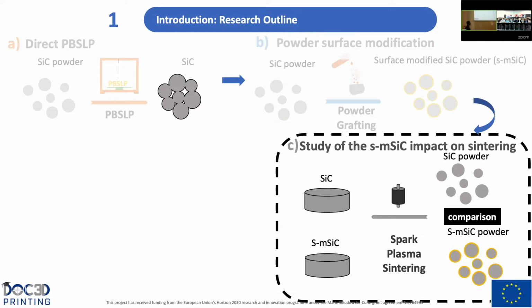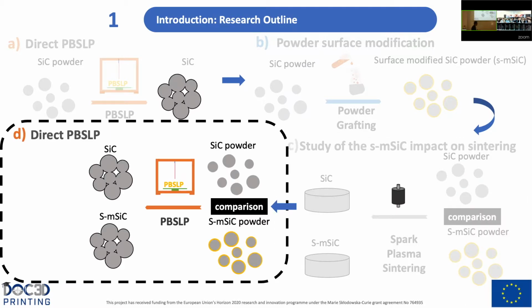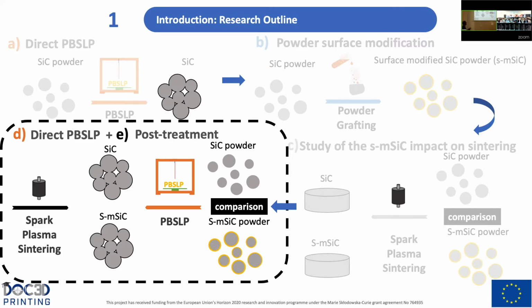After that, what we are going to do is to study the sintering impact of the surface modification by spark plasma sintering. And we are going to compare silicon carbide with the surface modified silicon carbide. And finally, we will use again the direct powder bed selective laser processing, this time to compare silicon carbide powder and surface modified silicon carbide powder. And we will use again spark plasma sintering as a post-treatment for the manufactured parts.